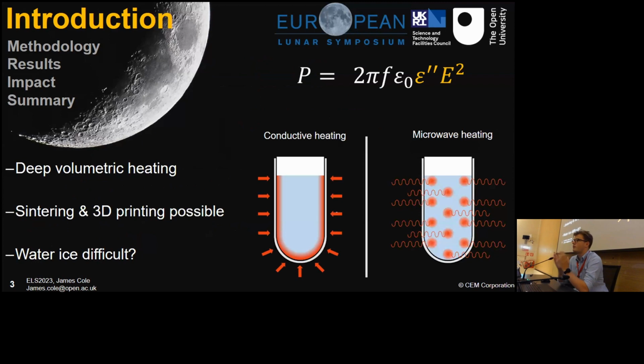So I'm going to quickly go over microwave heating and why it's of interest in the first place. As we know, most traditional techniques rely on conductive heating. So you have a hot region that the heat transfers through the medium towards the colder regions. This is a bit of an issue with lunar regolith due to the fact it's got very low thermal conductivity. So if you want to heat a large area, it takes quite a long time. Microwave heating, on the other hand, with the use of electromagnetic waves, polar molecules that are in the sample will rotate back and forth, and this creates kinetic energy and therefore heat, and can do so quite efficiently and can heat up the entire volume at once.